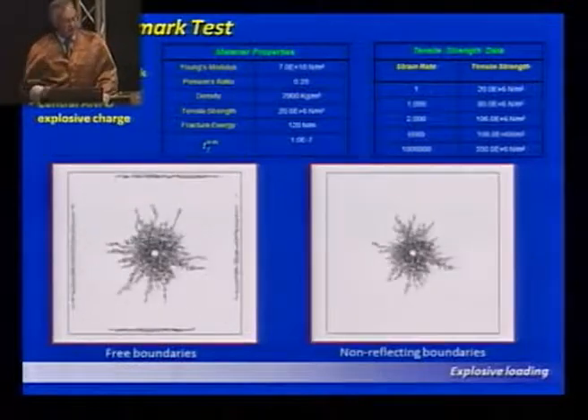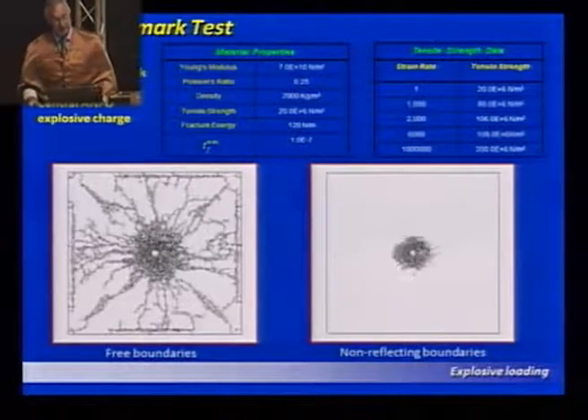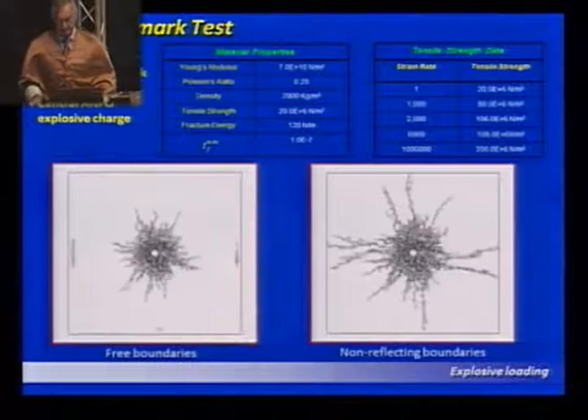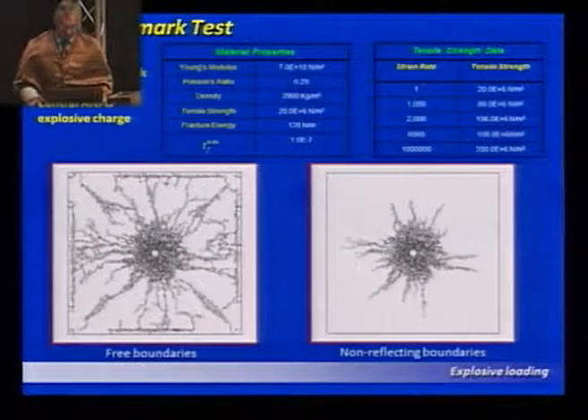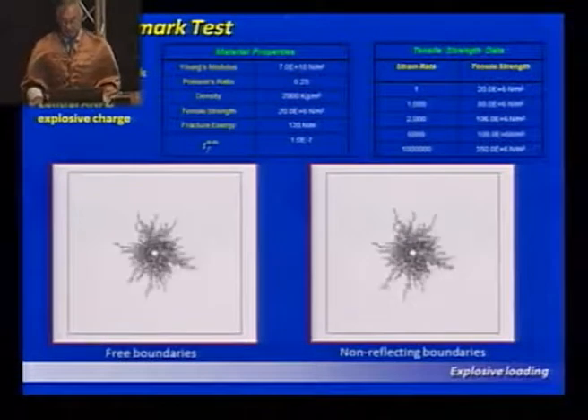On the top right there, it also shows you that the materials are highly strain rate dependent. As you increase the strain rate, the tensile strength changes by at least an order of magnitude.